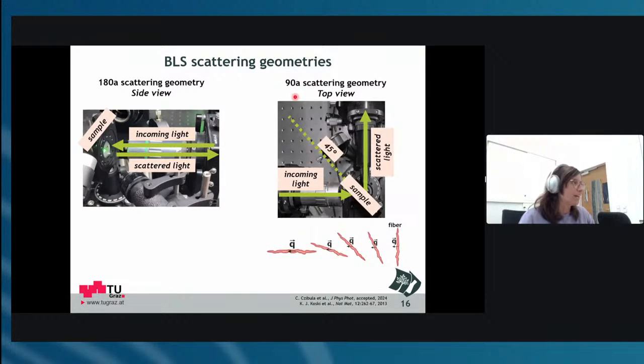This is for the 90A, it's a top view. Here we have the incoming light, and the scattering light goes here. This is 90 degrees, and the sample is oriented, as I mentioned, at 45 degrees. Now you can imagine if it's horizontal, it would be lying in this plane. And as I turn the fiber in this geometry to different angles, at 90 degrees it would be looking right at you.